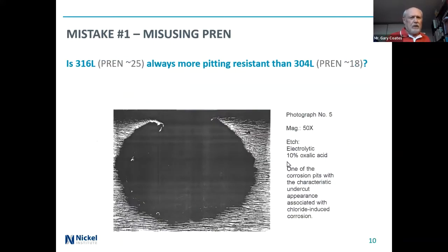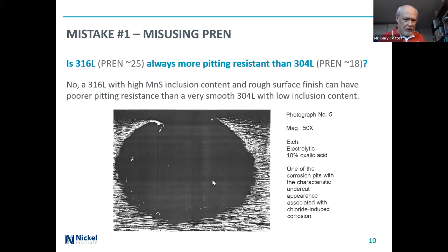So the next question to ask is: is 316L, which we saw has a PREN around 25 or 24, always more pitting resistant than 304L, which has a PREN around 18? And the answer is no. We have seen and documented where a 316L with a high manganese sulfide inclusion content and a rough surface finish can actually have a poorer pitting resistance in practice than a very smooth 304L with low inclusion content. And so you have to be very careful how you use PREN. It isn't a guarantee that one alloy is better than another. It may relate to the fact that one alloy is better if you compare the same surface finish, the same inclusion content, the same quality of heat treatment.